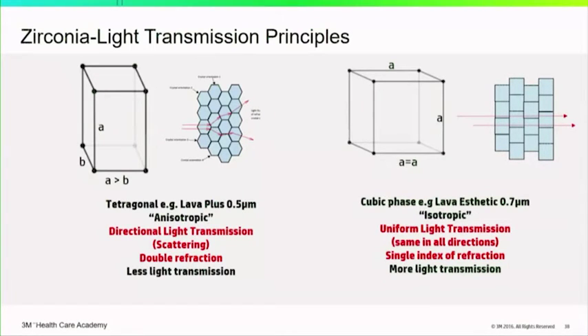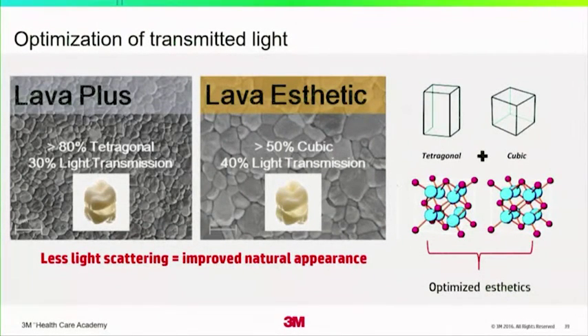And as you can see here, there are obvious differences because in this particular case, more light transmission actually comes through the material itself. If you look at two slides here, the difference between Lava Esthetic and Lava Plus, I don't know how they do this, but they've actually been able to optimize the crystal size itself. So there's a mix of cubic and a mix of tetragonal in the material. And because we have less light scattering, you get the more natural appearance that we've all been looking for. In optimizing the aesthetics, and considering that this is intended primarily to be used in a monolithic form, I think doctors are going to be very pleased with what they see, particularly as we move a little longer through the program.